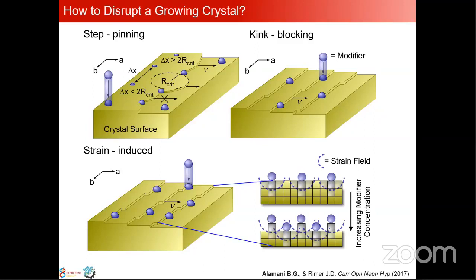So the first one is step pinning. What happens here is that you have a crystal, you have the steps, and your inhibitor or your modifier tends to pin on the edge of the steps. You also have a modifier which is pinning on the kink sites. So that's the kink blocking mechanism. And recently discovered in our group back in Houston, strain-induced dissolution, where the presence of the modifier tends to put a strain on the crystal surface, therefore inducing dissolution.